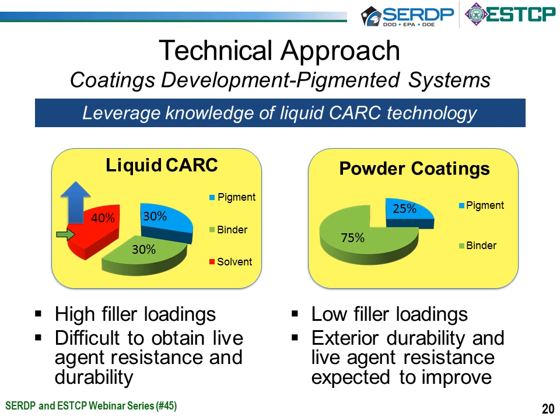solvent. So these are typically high filler loading levels, and high filler loading levels typically make things less exterior durable, and they make things somewhat absorbent to chemical warfare agents. So we knew those were some of the weaknesses within liquid CARC, the high amount of pigment. So the strategy on developing a powder coating was to have a binder-rich system. So we're looking at 3 to 1 parts of binder to pigment, a lot less.